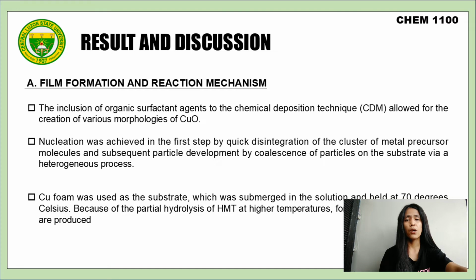As a source of copper 2+, copper sulfate was employed. There was no precipitation when HMT was introduced to the copper sulfate solution, unlike ammonia or other complexing agents. Copper foam was used as the substrate, which was submerged in the solution and held at 70 degrees Celsius. Because of the partial hydrolysis of HMT at higher temperatures, formaldehyde and ammonia are produced.